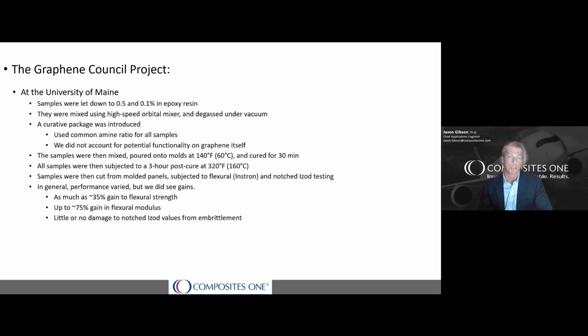Now, in some of the samples, we saw great improvements in both flexural modulus and strength. But typically, when you improve the modulus of resins, you have a negative impact on the toughness of the system due to embrittlement. And this was true for some of the samples. However, there were some that showed negligible impact to the toughness of the resin while providing excellent flexural modulus and strength improvements. So let's just dive into the details of the results.